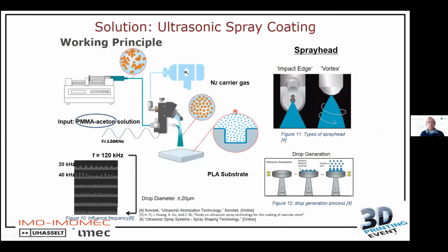So here you see the working principle of the ultrasonic spray coating system. So you have your ink, which is loaded here in the syringe, and then your ink, this can be, let's say, a solvent in which you have a polymer or nanoparticles sitting. In our case, we use a PMMA as a polymer in an acetone solution, and later we add some nanoparticles. We bring that to our ultrasonic spray coating system, and in here you do an ultrasonic vibration, and that is shown here below in this figure, where you see that the ink flows over our ultrasonic spray head, and by ultrasonic vibration you create standing waves.